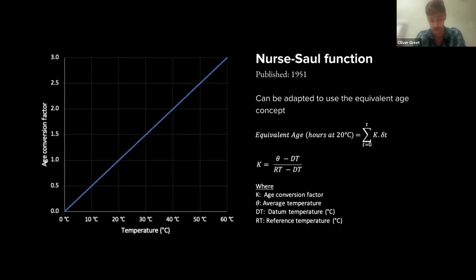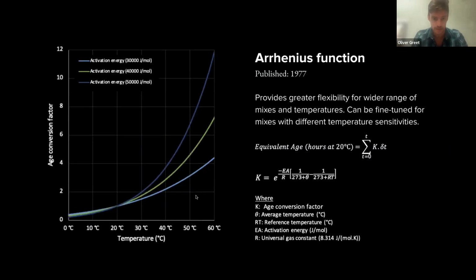This function is still in broad use today, but the second function allows you to adapt it for different chemistries. So particularly with the use of ground granulated blast furnace slag, or GGBS, today, the actual influence of this, as some of you may know, is that it increases the sensitivity to temperature. This means as we elevate the temperature, we get a disproportionate increase versus a Portland cement concrete. And conversely, at lower temperatures, which we're more familiar with in the UK, you see a reduction in the rate of strength gain.